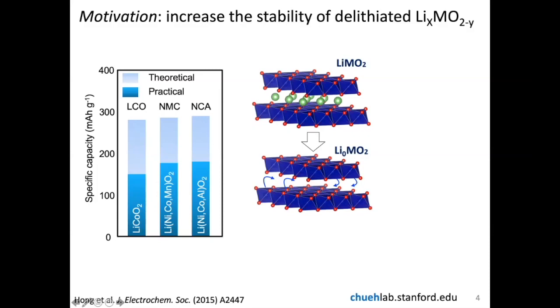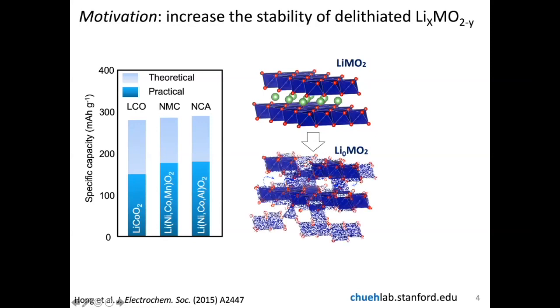But the problem is that as you delithiate and remove the lithium, the layer structure, which enables the fast transport of lithium, becomes quite problematic. So ideally, what you want to have happen is you remove the lithium, but the host structure remains stable. But in reality, what happens is that as you remove the lithium, the material disorders, the transition metal ions and oxygen begin to move within the material, thereby causing the material to degrade, especially in terms of lithium transport.